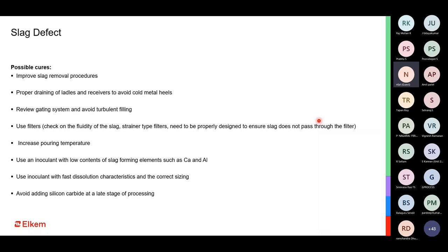Possible cures: first and foremost, we have to improve the process of removal of the slag. The slag removal process should be as late as possible so that you are able to remove any slag which is generated before the casting. And you thereby also take care of the slag which comes in from the furnace, the slag which comes in during magnesium treatment, the slag that comes in with the inoculant or any other additives. Like, for example, people do add alloys into the ladle before casting to get better recoveries, and there could be a tendency for slag generation from those additions. And of course, if our ladles are open, they would be in contact with atmospheric oxygen, which would increase the possibility of slag generation.